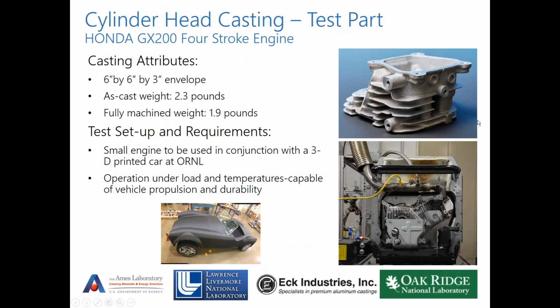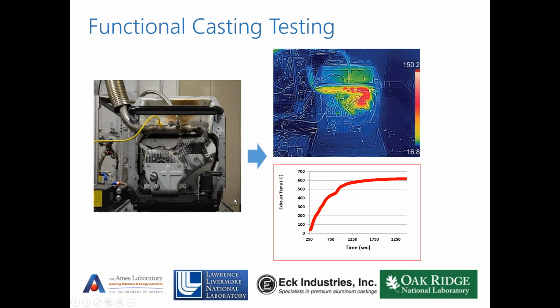We produced the cylinder head casting early on in the program, kind of as a demo project. This was at Oak Ridge National Lab, where they 3D printed a carbon fiber car, and they wanted an engine to drive it. And so what they chose is a Honda GX200, a 4-stroke generator engine. And we produced the cylinder head for that in this alloy, and that was all done in rapid prototype as well. This was done in the aluminum-cerium 0.4 mag alloy. And then it was tested. The vehicle was actually driven. There were exhaust gas temperatures of at least 600 degrees C, and everything went well with the demonstration.